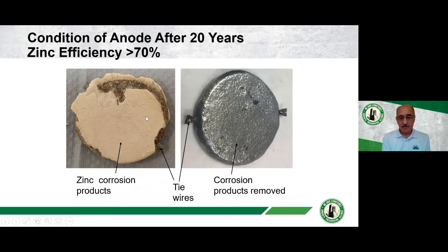At 20 years we did the same thing, obviously. 10 more years later down the line, and you can see that there's quite a chunk of corrosion product on the surface of the anode. We then removed the corrosion products and had the bare metal left behind. And you can see that it's still pretty intact, really, within reason. Obviously we've lost a lot of zinc, but it's still there, and it can continue to produce current.